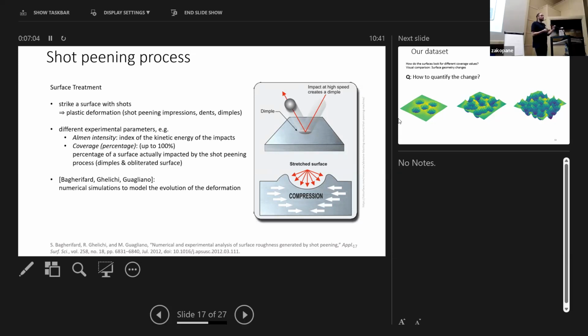It's also used in applications, for example, medical applications where you might have some metal in your bone to fix a broken leg. You need to implant it, and the question there is this offset. On one hand, you want bacteria to have trouble adhering to the surface, and on the other hand, that it is better accepted in your bone. There you can see that depending on how long you keep on shooting the surface, there is an impact on the bacteria adhesion, as well as how well it is accepted as a bone replacement.